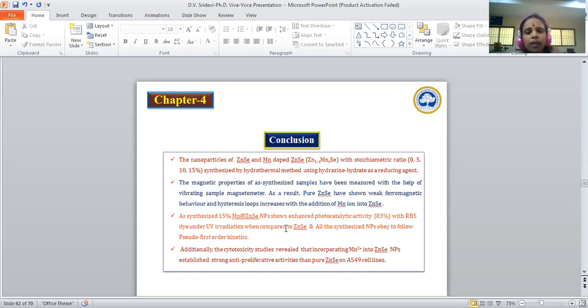The as synthesized 15% manganese doped zinc selenide nanoparticles show enhanced photocatalytic activity. That is, 83% enhanced photocatalytic efficiency was observed at 15% manganese doped zinc selenide nanoparticles using RB5 dye under UVA irradiation when compared to zinc selenide. And all the synthesized nanoparticles obey pseudo first order kinetics. Additionally, the cytotoxicity studies reveal that the incorporation of manganese into the zinc selenide nanoparticles established stronger anti-proliferative activities than pure zinc selenide on lung cancer cell lines.